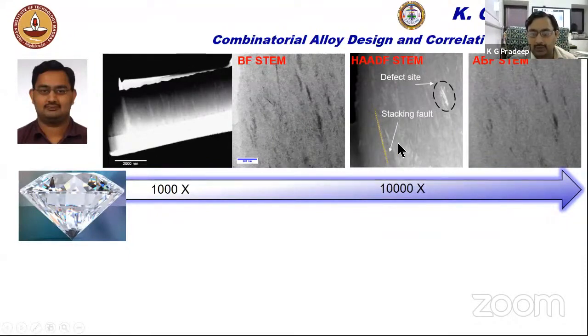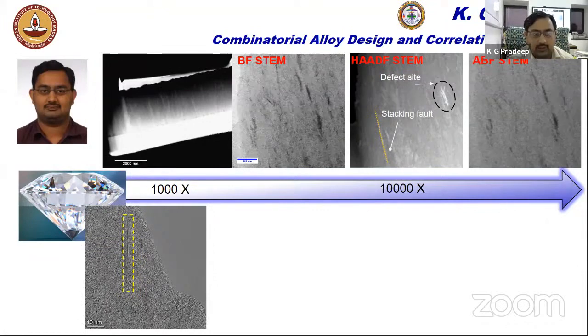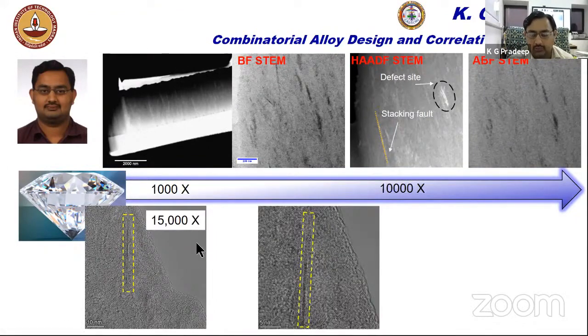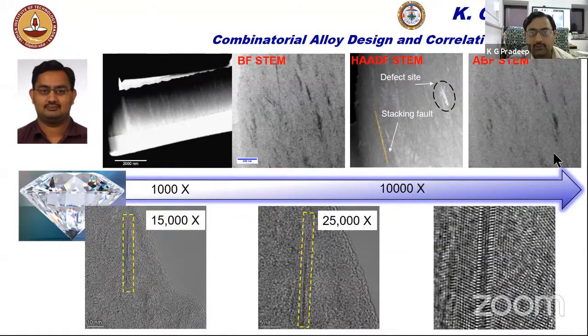Now you will be able to identify locations like defects, like stacking faults, and there are other clusters of defects together, which are bright contrast in a dark field image or high angle dark field image. Now, even if you want to know further details of this defect structure, you can go even higher in magnification. That means you can try to resolve the stacking fault in even higher detail. Now we increase the magnification by 15,000 times, you see something more. You increase it 25,000 times, you see even better. Now we are getting close to a situation of revealing the details of the defects itself and its atomic organization.